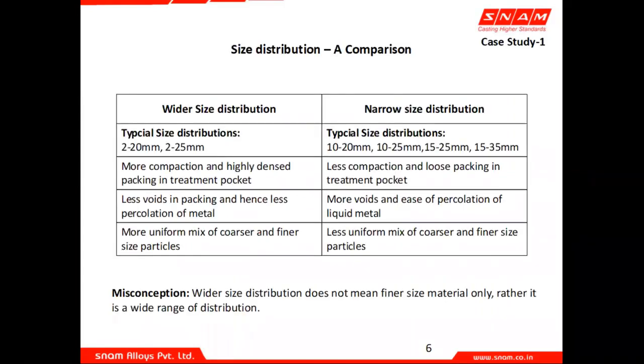So these are the 2 cases we have. On one side, I have a typical wide distribution, which is 2 to 20 mm of the nodularizer, or 2 to 25 mm. And on the other side, I have the narrow size distribution, 10 to 20 mm, 10 to 25 mm, 15 to 25, 15 to 35. And we will see, by measurement, how 2 to 20 provides a better compaction, is more dense.